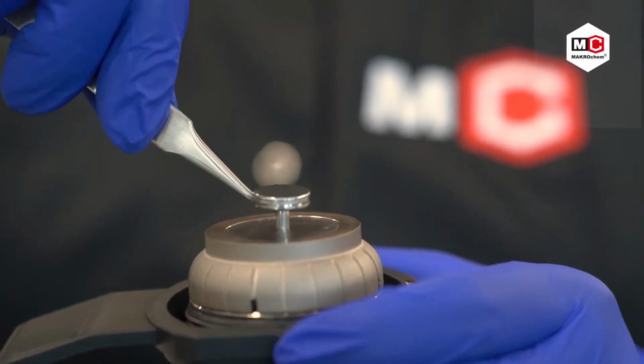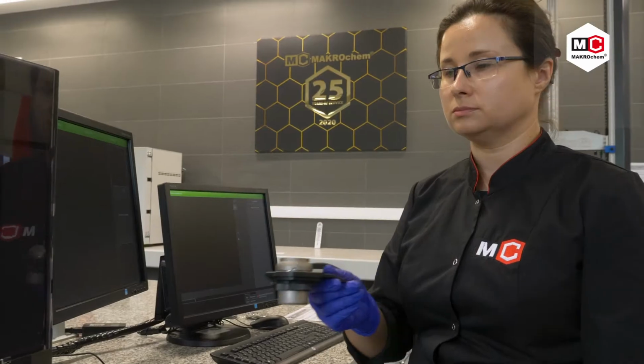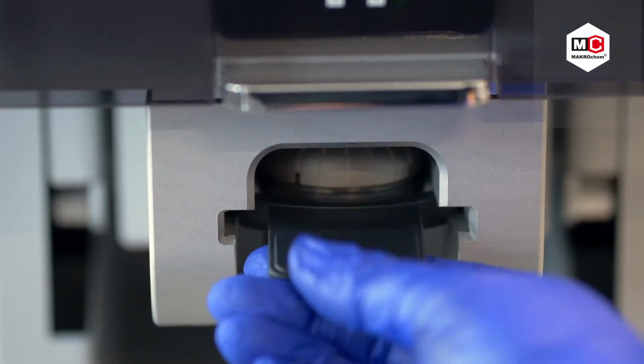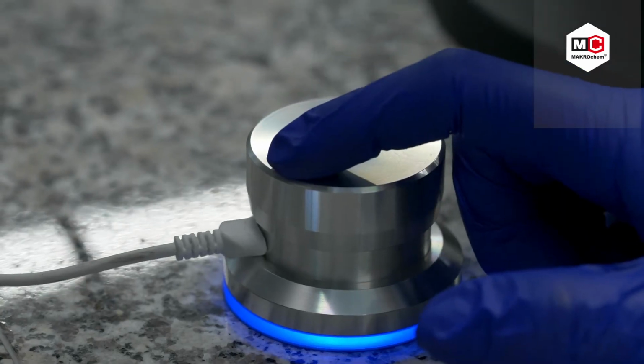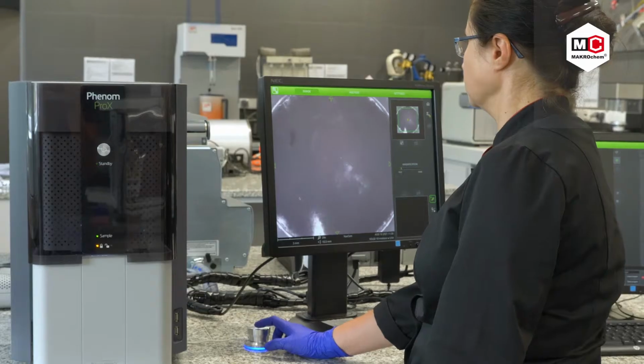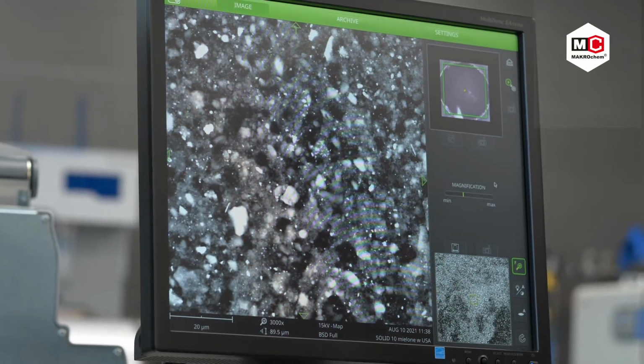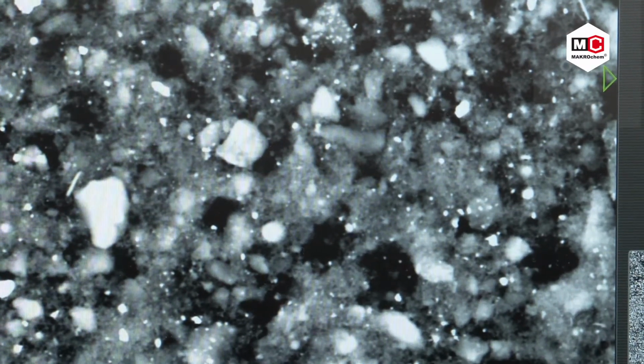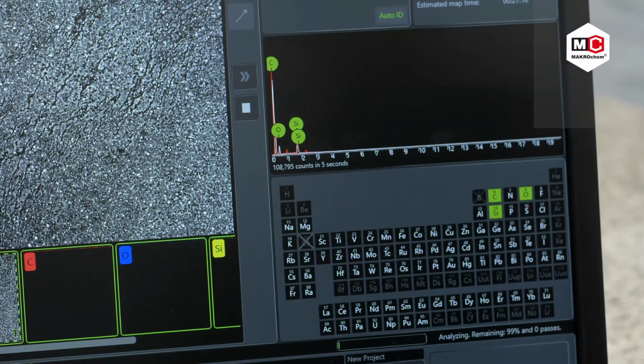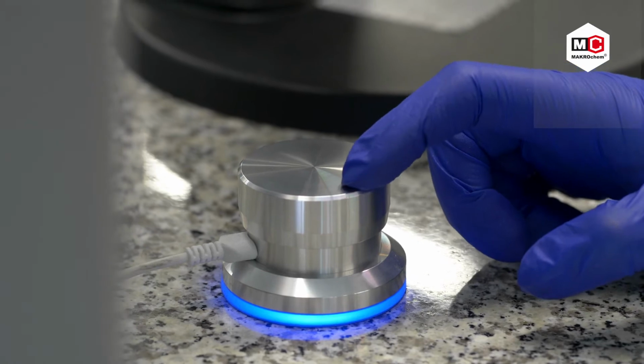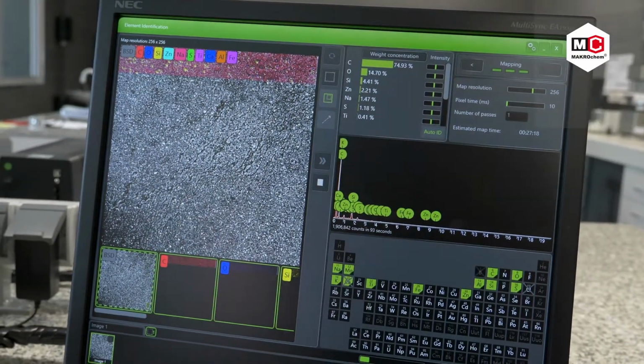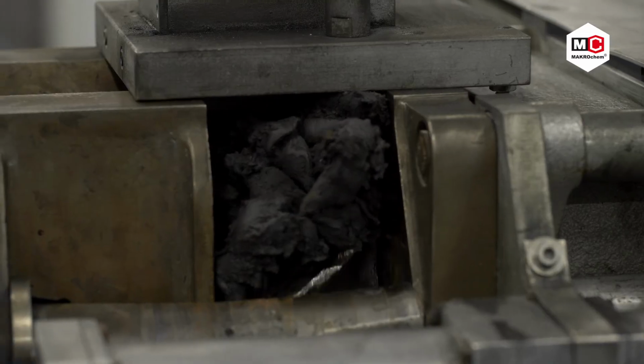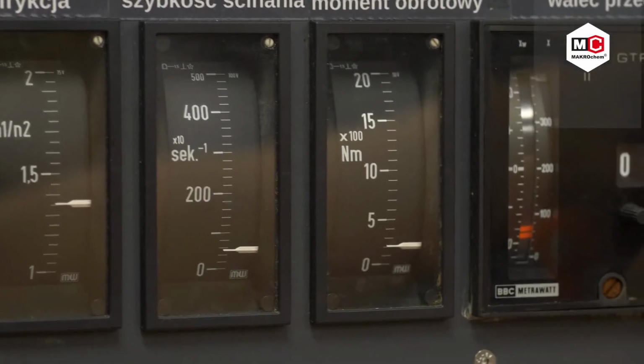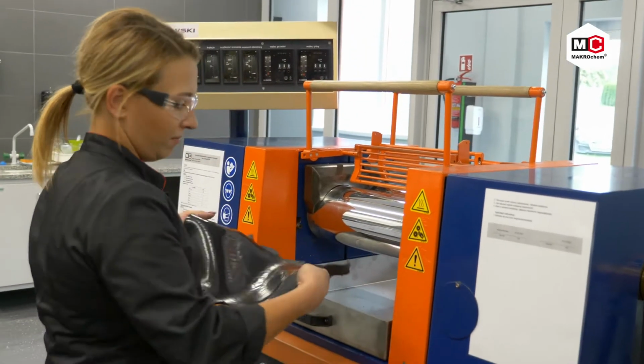The next test of content of carbon black and its morphology consists of imaging and scanning of elements using SEM-EDX technique. This measurement allows us to observe the size of carbon black particles, composition of aggregates, and the size of grain of carbon black in free form and in rubber composites. EDX allows us to perform quantitative and qualitative analysis of elemental composition of carbon black. We analyze the impact of carbon blacks on the production of rubber compounds in lab Banbury-type mixer and two-roller mill.